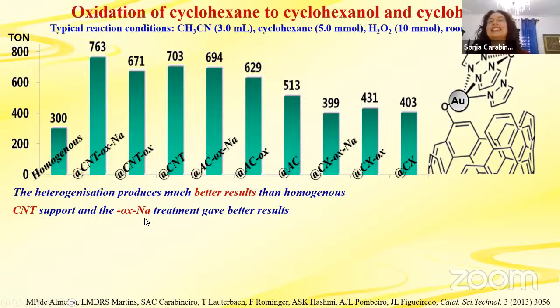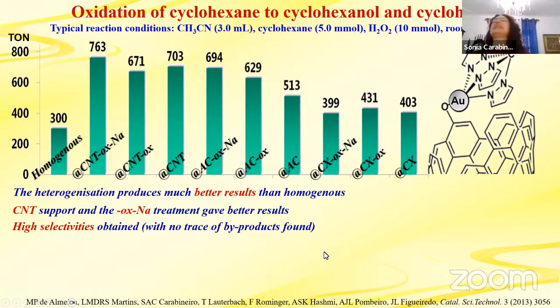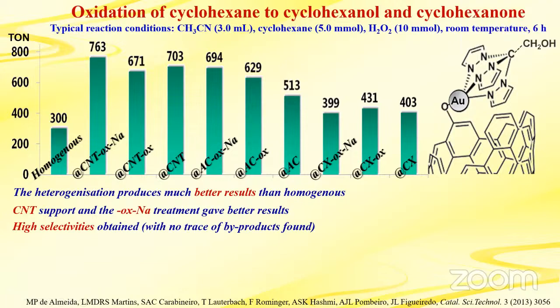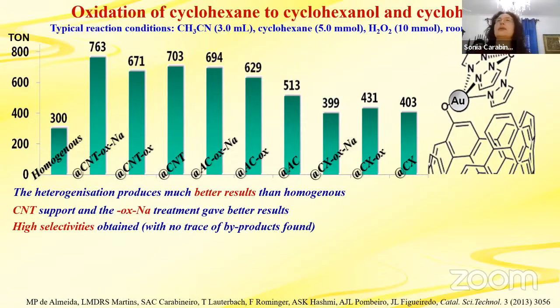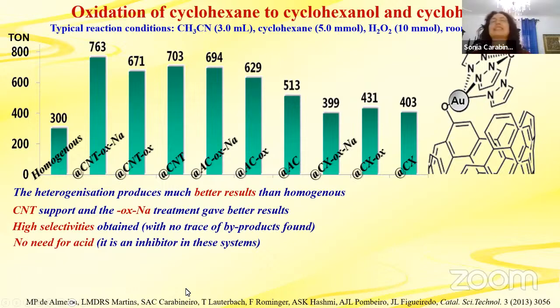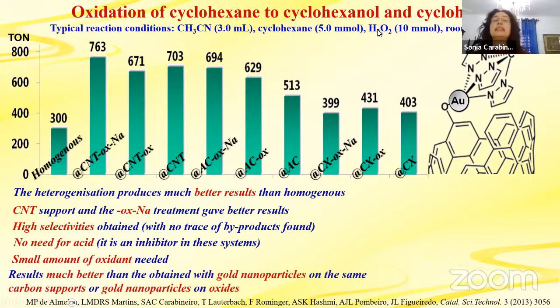So we see here that these were the best results, and in all cases, high selectivities were obtained. So no trace of byproducts were found, only cyclohexanol and cyclohexanone. And there was no need for acids, because sometimes we need to use a little bit of acid to acidify the medium for the reaction to be better, but it was not needed. In this case, it's even an inhibitor in these systems. And also, only a small amount of oxidant was needed. So here, only 10 millimoles of hydrogen peroxide.